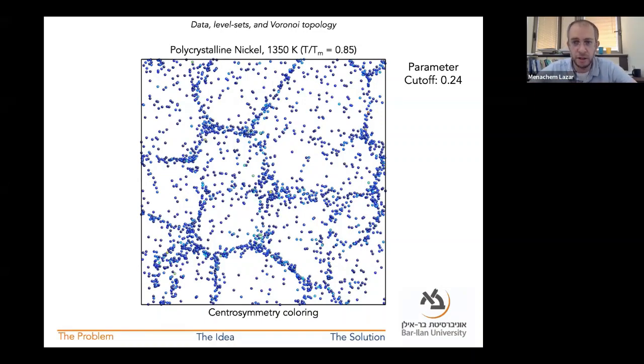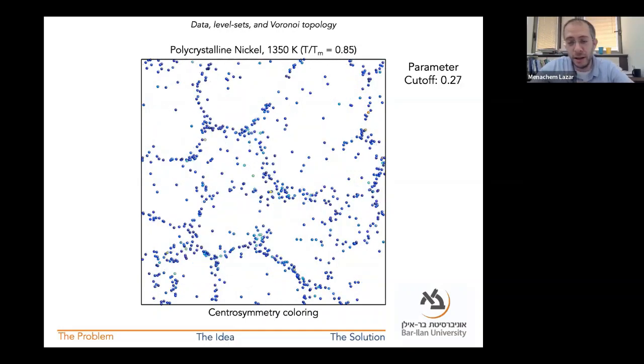Material scientists, the computational kind, have ways of dealing with these things. Sometimes they'll cool a system down before they do the analysis, or they'll take some average over time, which, remember, this is the engineering perspective, so it's okay. As long as it works, it works. And that's really all we need. But if you're the mathematician, you feel like maybe you're missing something. Maybe we could say something more, or maybe there's a nicer picture of what's going on. So that's what I want to tell you about.